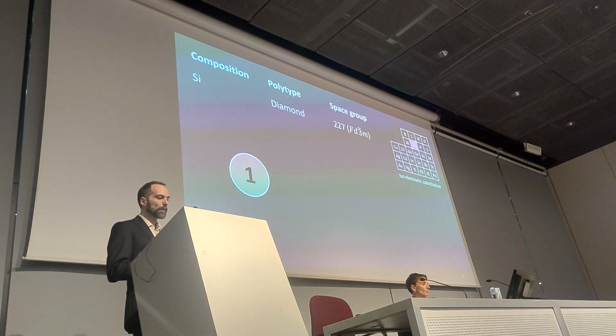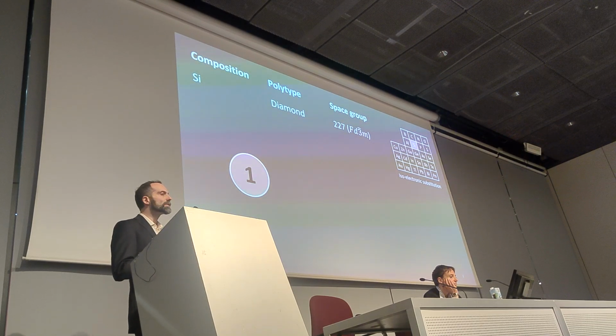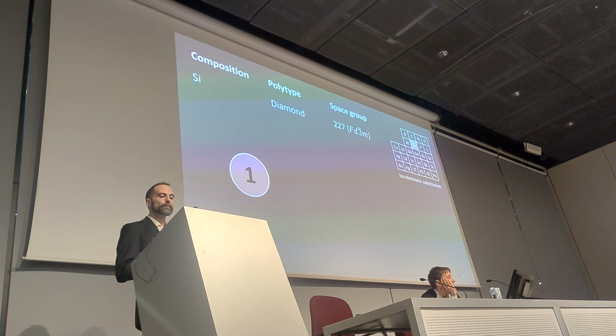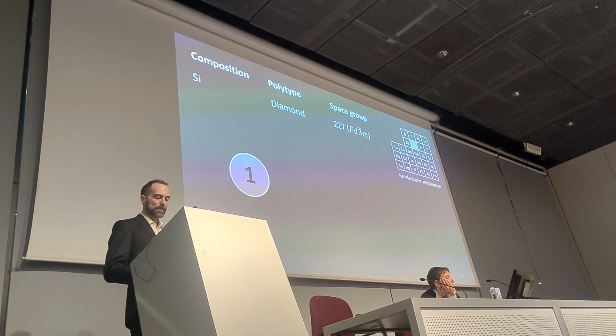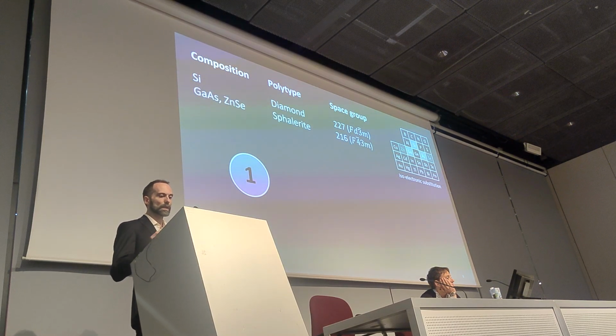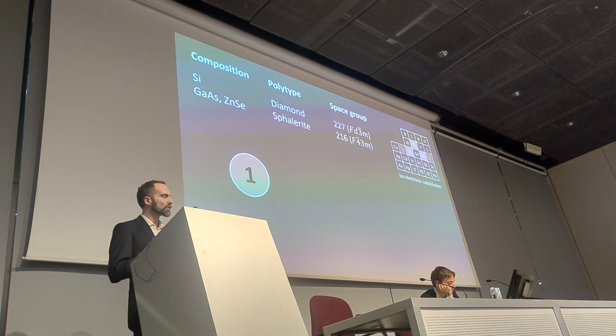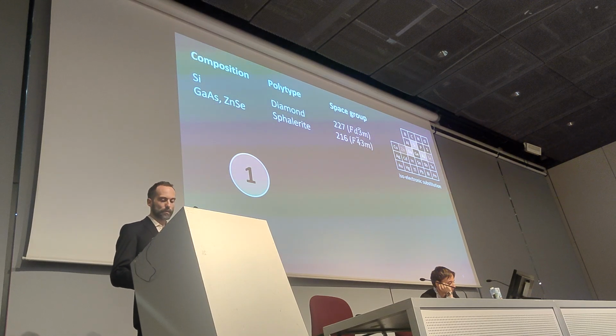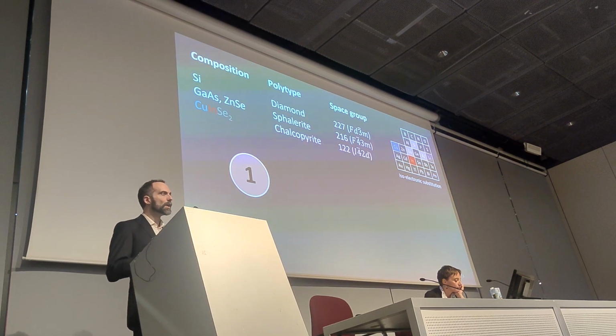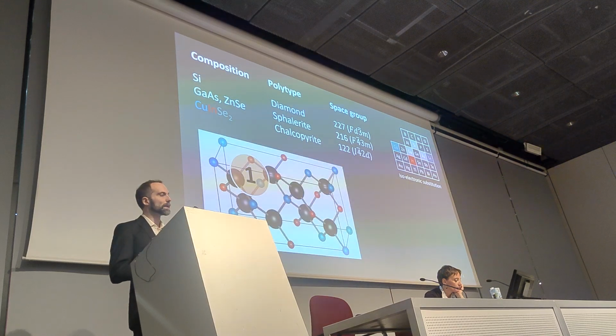Looking at the bulk properties of the material, we can derive CIS, copper indium diselenide, by isoelectronic substitution from the diamond structure of silicon. So if we substitute silicon with gallium and arsenic, or zinc and selenium, we get isoelectronic substitution, and of course we decrease the space group symmetry, but we get the same number of valence electrons. Now, imagine we have the zinc selenide zinc blende structure. You now replace the zinc atoms with half of them copper and half indium. You double the unit cell, and we get the copper indium diselenide structure, which is shown here.